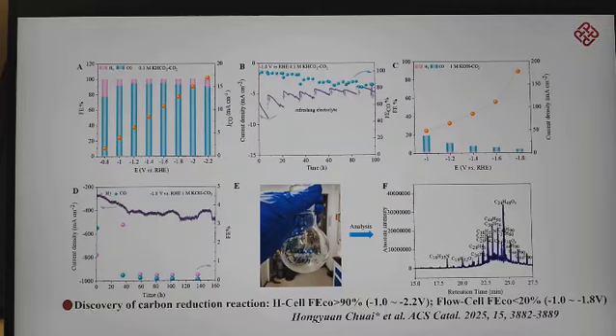So we think there might be some liquid products generated, but NMR tests did not detect any common liquid phase products, such as formic acid, methanol, or ethanol. We hypothesize that long-chain organic compounds may have been produced, which are insoluble in heavy water. To collect the liquid phase products, we performed electrolysis at -1.8 volts for 160 hours. By extracting the electrolyte after the reaction, we obtained the white powder-like product shown in the round bottom flask.